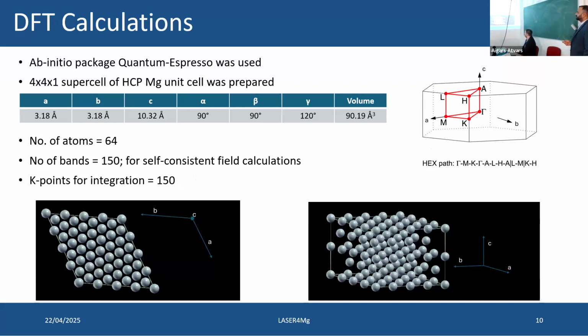So here is a synopsis of the DFT calculations. This is a free-to-use package known as Quantum Espresso, and I made a 4x4x1 supercell of hexagonal pure magnesium to do these simulations. So here is the lattice that was used for the simulations. The number of atoms is 64. These two things are parameters for running DFT simulations, and here there is an illustration of the high symmetry points for the Brillouin zone of hexagonal lattices. So around these points, the calculations are done.